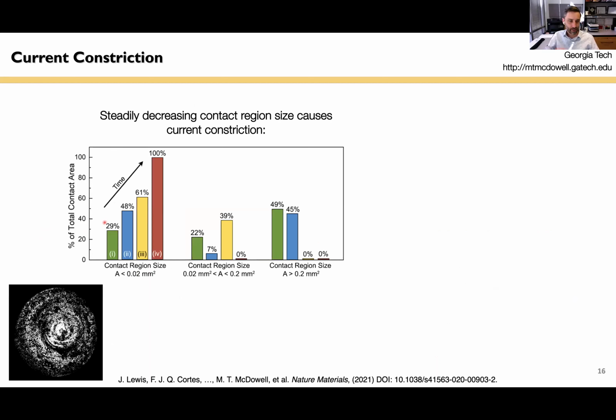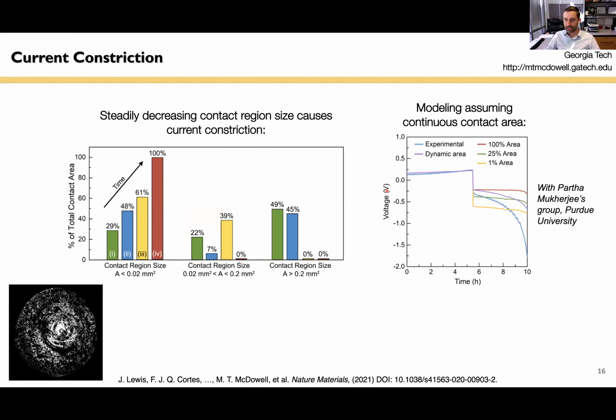We quantified the change in contact size with time. And we found that at the end of the experiment, 100% of the contacting points at this particular interface had this relatively small size, less than 0.02 millimeters squared. And we worked with Professor Mukherjee's group here at Purdue. They did some modeling of our cells and the materials and geometry of our cells to try to see if we could recreate the electrochemical curves we measured with the overall contact area loss that we measured.